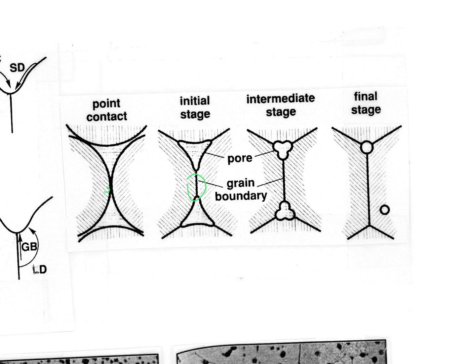And you want to try to get this out, and when these pathways, these pores are continuous, it's like squeezing a sponge. Air comes right out. All right, just no problem at all. But then, and you'll see this somewhere around here and certainly there, those pathways to the surface get cut off. All right, everything keeps shrinking and shrinking and shrinking, and eventually the pores are isolated. And then that nice pathway of just squeezing the sponge and getting the air out stops. All right, and then at this point, diffusion rears its ugly head. So we can no longer squeeze the sponge. We have to rely on diffusion to get this out. Diffusion, again, slow. All right, we don't always think of diffusion as slow, but there are different types.